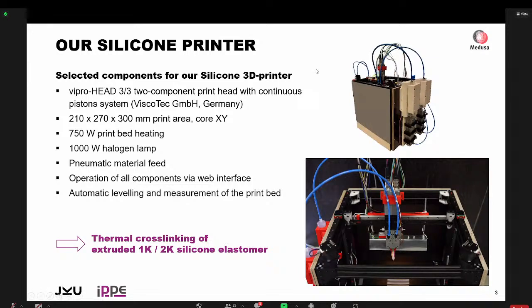This is a very good point. Actually, this system is not made for fine details. With this extrusion, and because it's dealing with liquids, I would estimate 0.5 millimeter accuracy. So it's not made for fine details. But when you imagine we have to print whole brains, so we need the mass more than the details. So in order to produce bigger parts, we are dealing with anatomical models, not with implants that need special biocompatibility.